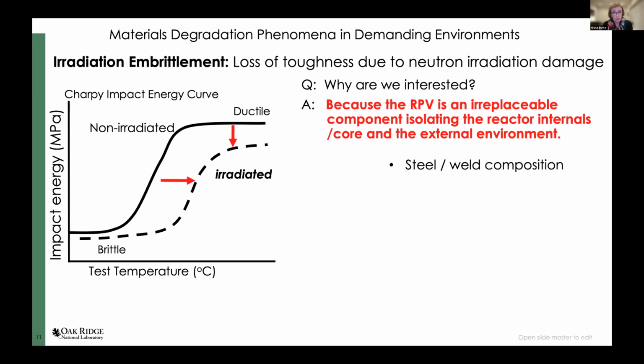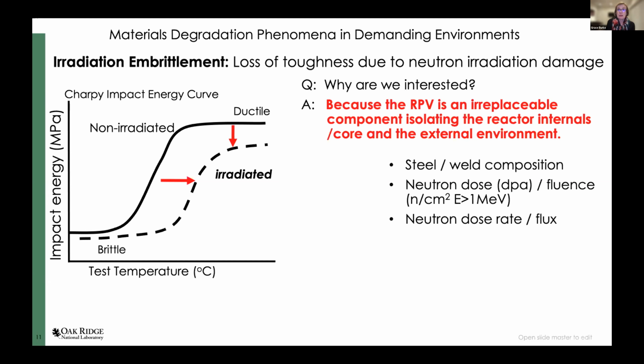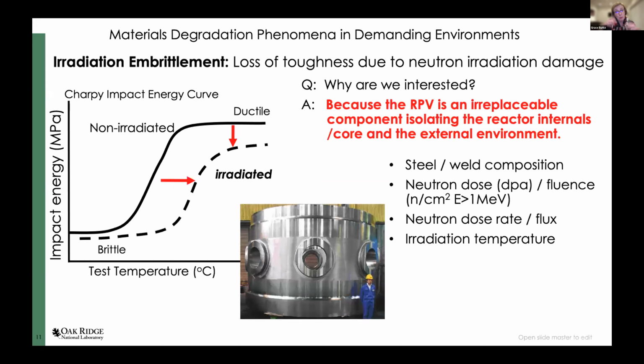So the factors that we're interested in, in terms of studying this degradation, are the composition of the steel or the weld of interest. We're interested in the neutron dose or fluence and the dose rate or flux, as well as the irradiation temperature. These will all have a big effect on the material. To give you an idea what we're talking about here, since a lot of us tend to work with fairly small specimens, this is a ring forging that is in the beltline region of a pressurized water reactor. And here is our equivalent scale bar. Here is one of the engineers involved with construction. So they're quite large.